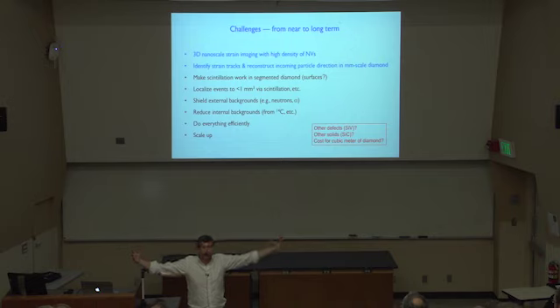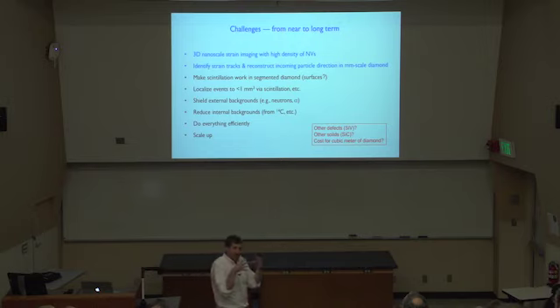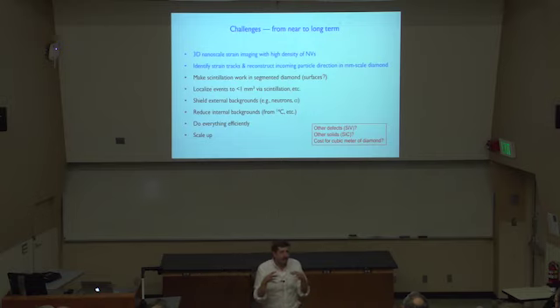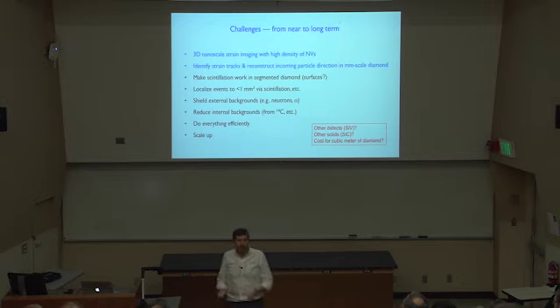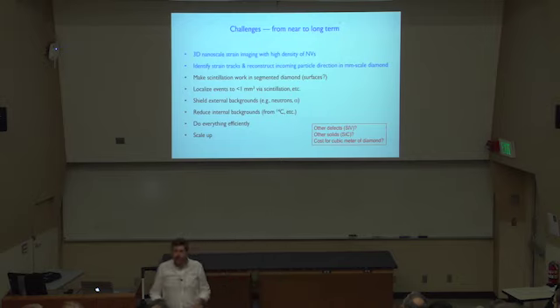All right? We might not just use NV sensing. We might do X-ray or cathodoluminescence measurements to localize this kind of needle in a haystack problem more, right? You're going to have to control the strain background in your diamond and understand this, because you're looking for an added defect on top of what might be there naturally. So we have to work on making the diamond uniform enough. We've done a lot of work on that, but more is needed. And you have to scale everything up. Maybe this works on one little cubic millimeter with heroic efforts. Maybe we can inject something which makes a strain defect and find that little thing inside of there.